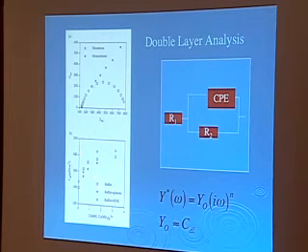And you see that independent of whether you have buffer around or enzyme or things like that, and we're doing this as a function of the cobalt hexamine concentration, which of course makes the things work better, that while there is some change in capacitance with concentration, it's modest. We go from 140 microfarads per square centimeter to 180 microfarads per square centimeter. That's not enough to dramatically change the charge transfer kinetics again. It's a very modest change in the capacitance. So we rule out playing with the double layer as where this comes from.